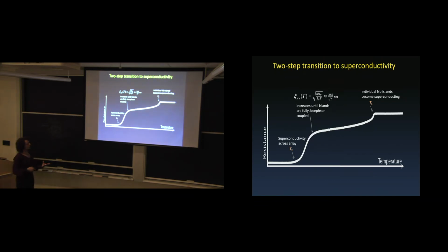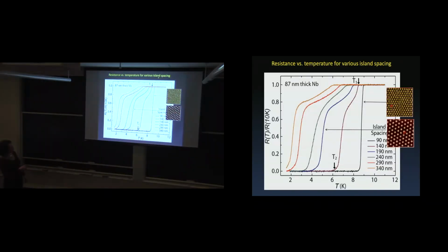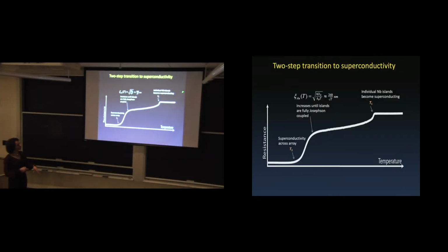So it's a two-step transition, as you can see here, right? There's a T1 up here, one step here, and then there's another step there. Okay? And that's expected because the first transition is where the islands go superconducting, and then the resistance stays pretty constant as the coherence length of the gold increases, and then at this temperature, the coherence length of the gold equals the spacing between the islands, they become coupled, and the resistance drops to 0 across the array, which we call T2. So a two-step transition is expected.